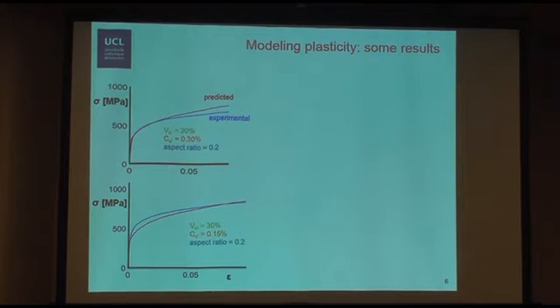The correspondence is not bad, but there still is a little gap here. It can be explained by two reasons that we already know. Firstly, for the first graph, experimentally the martensite volume fraction is a bit lower than 20%, that's why the experimental curve is under, and here it's a bit above 30%, while martensite volume fraction has a great impact on the elastoplastic behavior. The second reason is that there's no stage 4 included. We use a Swift type law for the ferrite that keeps on increasing. That's why the predicted curves keep on increasing, whereas the experimental curves reach kind of a plateau.